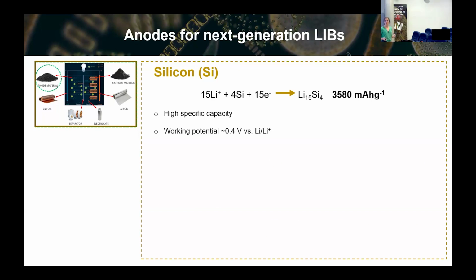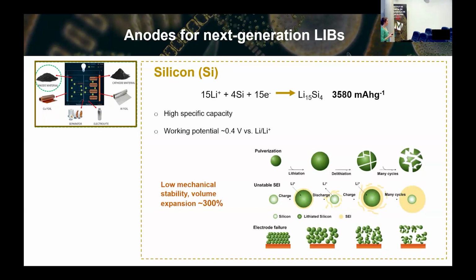And this will actually cause some mechanical instability on the anode, because we'll start with the appearance of some strain, then crack formation inside the particles, then crack propagation, then pulverization of the material. Then when the material exposes new surface area, we have a new solid electrolyte interface being formed there. So it ends up with a huge capacity fade in just a few cycles. So a lot of effort has been put in the last years to try to make silicon work. And some of the strategies that are more successful, I would say, are the nanostructuring of the material. Because if we create nanostructures, then we give space for the silicon to expand into the voids of the nanostructure. And so it should last longer.